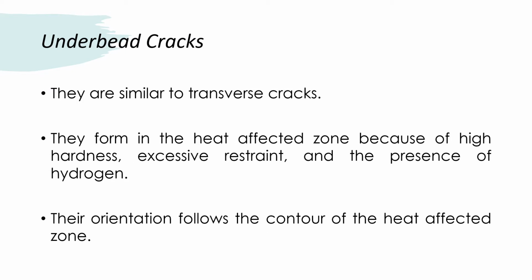Next is underbead cracks. They are similar to the transverse cracks. They form in the heat affected zone because of high hardness, excessive restraint, and the presence of hydrogen. Their orientation follows the contour of the heat affected zone.